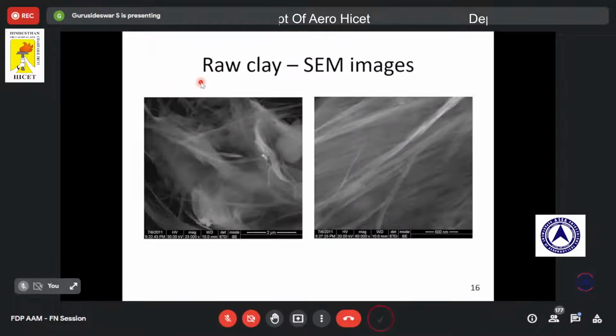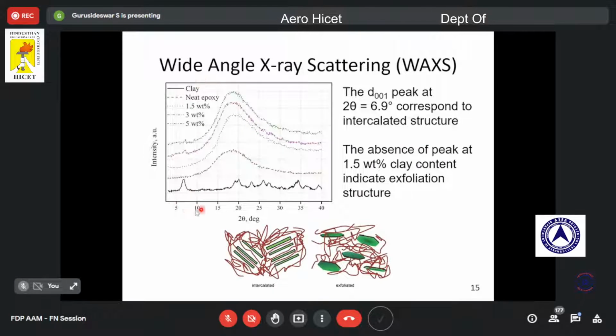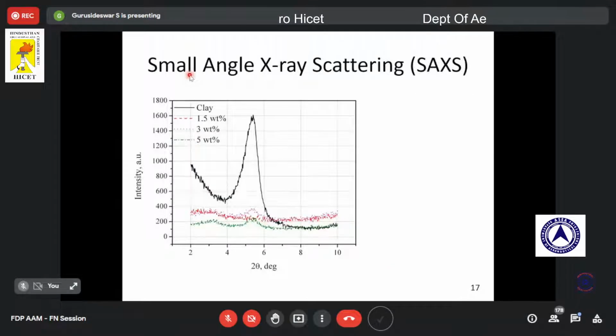If you see in wide angle scattering, the angle is from 0 to 40 degrees, but we wanted to focus only at small angles. Because we know that the D001 peak will correspond to the intercalated structure, we wanted to focus at smaller angles. So that is why we have done small angle X-ray scattering, from 0 to 10 degrees. So again we observe the same.